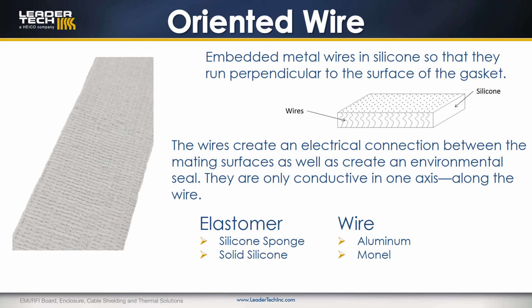The wire is crimped for additional resiliency and to optimize the mechanical performance of the gasket. It has between 700 to 900 wires per square inch. The material is available in strip or sheet form and can easily be die cut or laser cut into complex shapes or fabricated into custom frame gaskets.